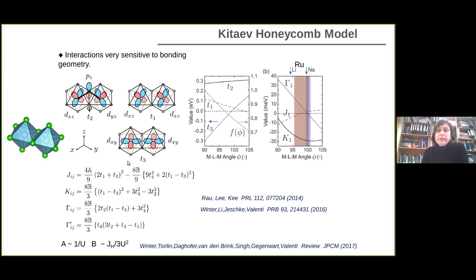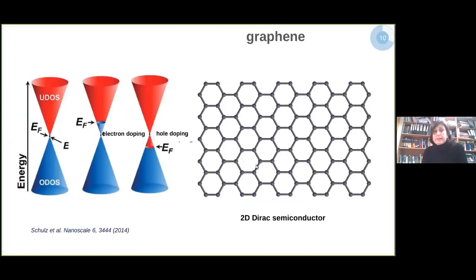And what I want to show here by using these analytic expressions for the magnetic interactions is that very small changes in this hybridization between the ruthenium, so basically small changes in these hopping parameters due to the change of this angle, introduces huge changes in the magnetic interaction. So I can go, if I am, for instance, in the 90-degree configuration, where I have an important Kitaev, but also a very strong gamma contribution, we can go by changing the angle into a region where the Kitaev interaction is a dominant one.